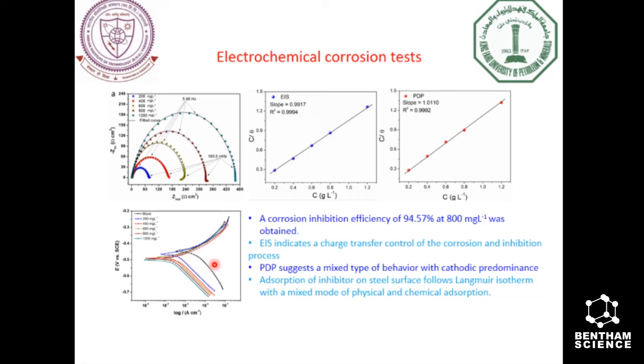And the adsorption of the corrosion inhibitor over the metal surface was tested using several different adsorption isotherms, among which the Langmuir isotherm provided the best results with a mixed physical and chemical adsorption.